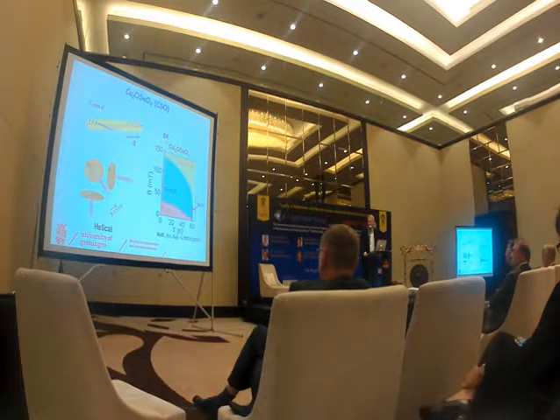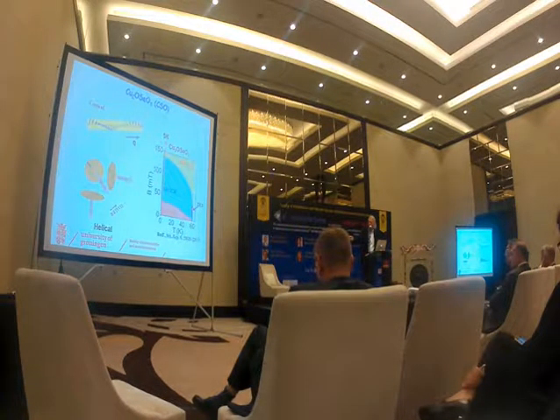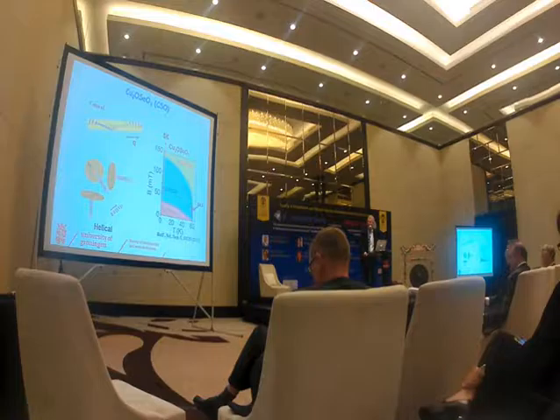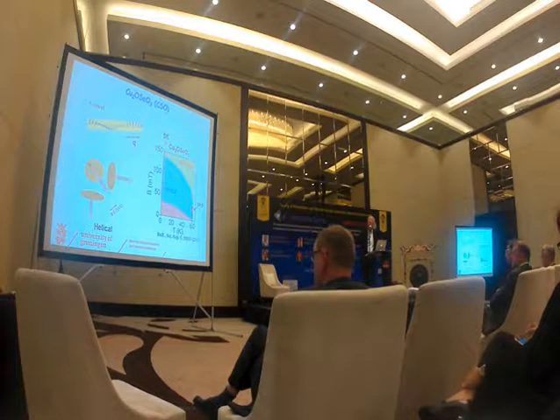This is the magnetic phase diagram of this copper oxoselenite. We see that at low magnetic fields you have a helical spin state, where the spins form helices perpendicular to the propagation vector. At slightly higher magnetic fields you have a conical spin state, where the spins form a cone with respect to the applied magnetic field. And you have to apply large magnetic fields in order to get the spins aligned with the magnetic field. In a very small pocket of magnetic fields and temperatures is where you obtain these skyrmionic states that we will explore further.